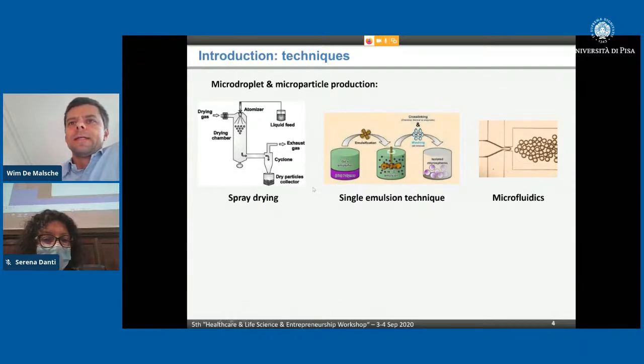So the end goal is typically making particles, and a conventional way of making particles is by spray drying, which has some limitations. A very common way of making droplets or emulsions is simply by mechanical means, by having an impeller which mixes the one phase into the other phase and ruptures the droplets into smaller droplets. But as said, this results in polydispersed systems. And it's well known, already for 20 years or so, that you can produce droplet by droplet under exactly the same conditions, and this can lead to monodispersed solutions.